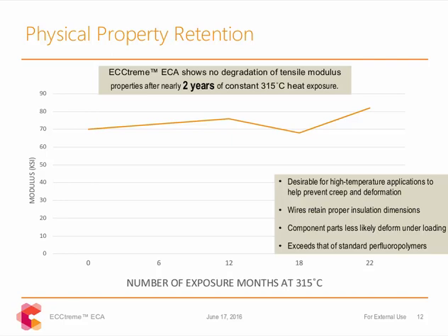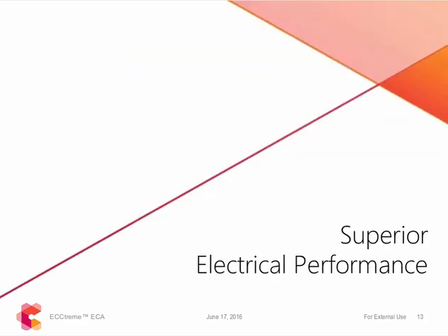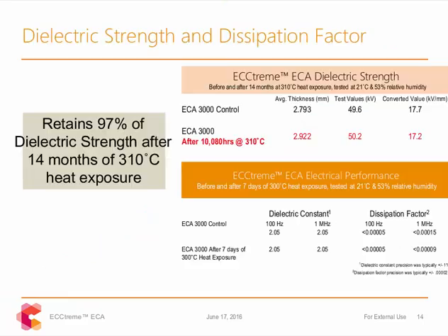It should also be noted that these thermal aging studies were performed at 315 degrees, which is 15 degrees above the continuous use temperature rating granted by UL. This limited drop in tensile and elongation is very impressive considering the conditions this material is being exposed to. Again, as I mentioned before, this material was initially developed for the wire and cable industry, so it was important that it maintain the same levels of electrical performance as incumbent fluoropolymer materials. And so I'll now give some examples of electrical performance for ECA.